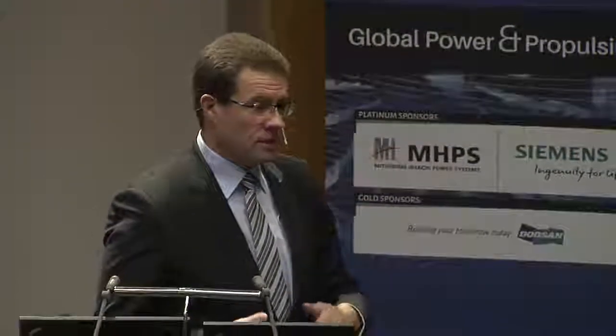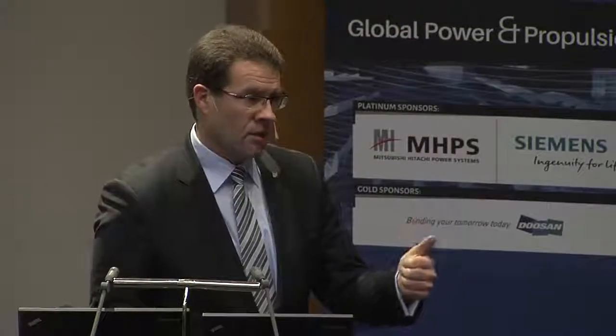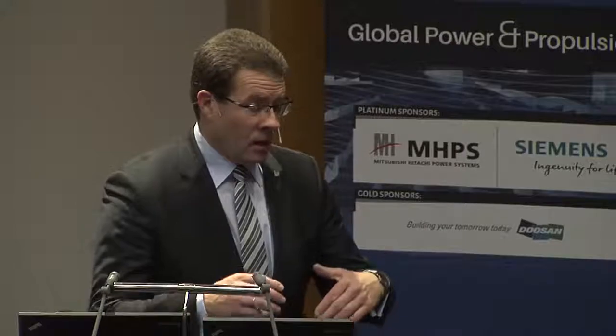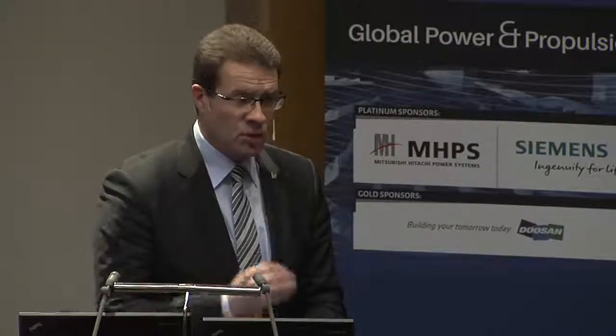For example, if we look at titanium, titanium is extremely prone to oxygen. So we need to take care of the oxygen content of the powder first. So we start with a low oxygen content in the powder. We need to take care of the process itself. So we need to shield the processing zone, the melting zone. We can do that by process gas, inert gas that protects the melting zone. We've looked at that very carefully for titanium blisk parts. And what we saw is that during the process, we increase the amount of oxygen in the part relative to the starting oxygen content of the powder by only 10%. So if you start with 400 ppm oxygen in a titanium powder, you will end up with 440 ppm of oxygen in the fully machined part, which is perfect in this case. If you don't do the shielding, you end up in trouble. That's for sure.